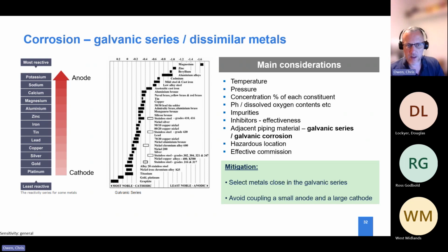And what you have now is a range of different materials sitting at different positions across the galvanic series. When a product is more cathodic, it's more resistant. As soon as the material is more anodic, then that material will corrode faster or sacrifice itself as a result of the electrochemical reaction. So when you start seeing stainless steel being added into these mixed metal hybrid systems, it starts to cause everything else below it in the series to accelerate faster. And this is where we start to see a lot of issues.